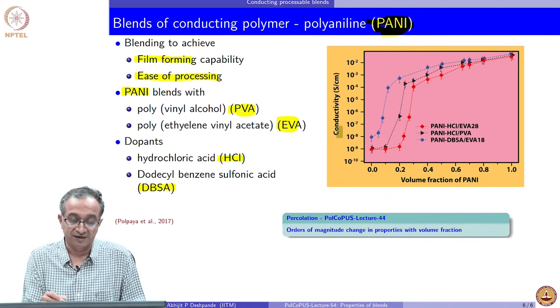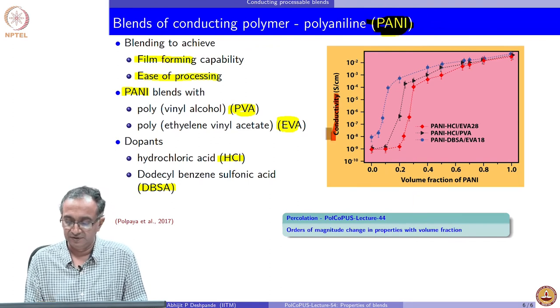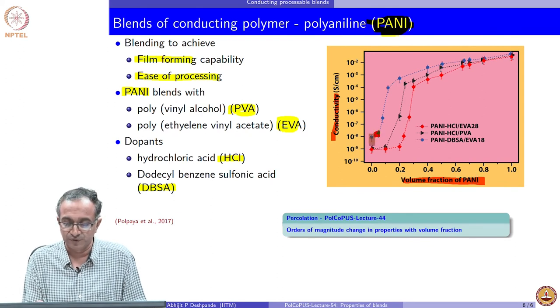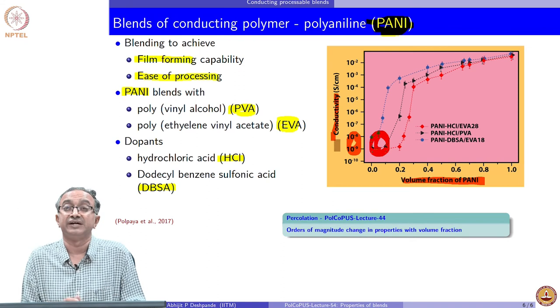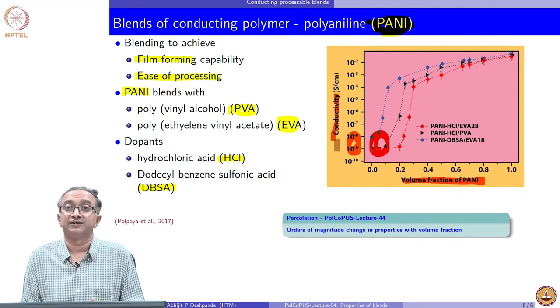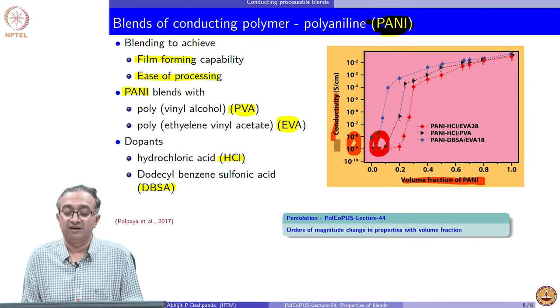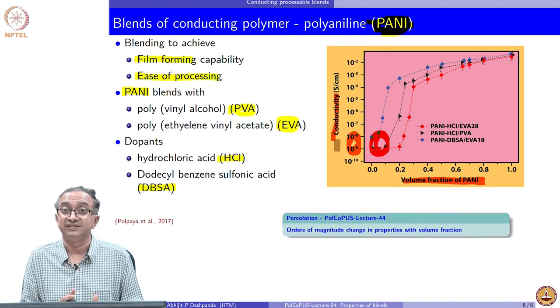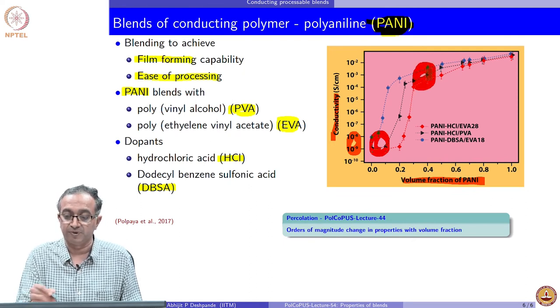What is shown here is conductivity as a function of volume fraction of PANI, the polyaniline which is being added. At low volume fraction, conductivity is very small. This is insulator basically. If you recall, 10 to the power minus 7 and lower values are insulators. This is mostly ethylene vinyl acetate, EVA as it is called or PVA, polyvinyl alcohol properties where the conductivity is very low. But look at how the conductivity varies as we keep on adding more and more polyaniline. What is remarkable about such blends is by the time we add about 30-40 percent of polyaniline, we get conductivity which is in the semiconducting range. This material can be used for a sensor or an actuator or any such application.